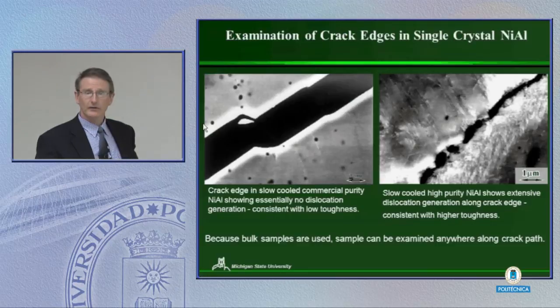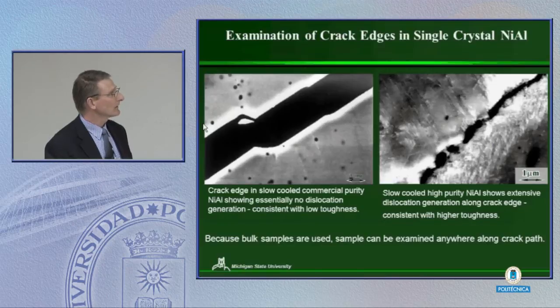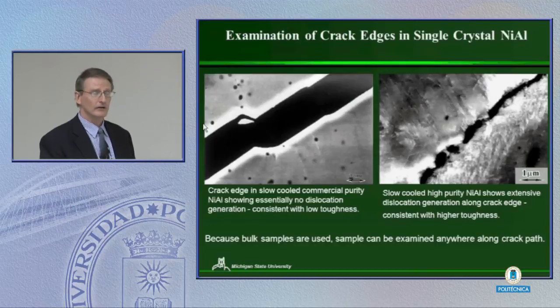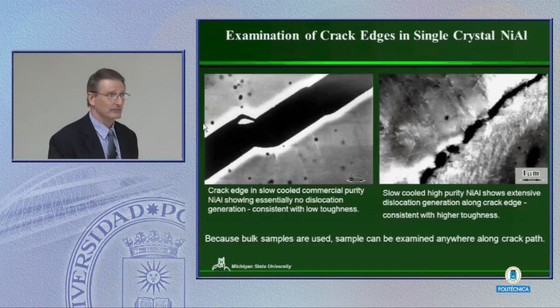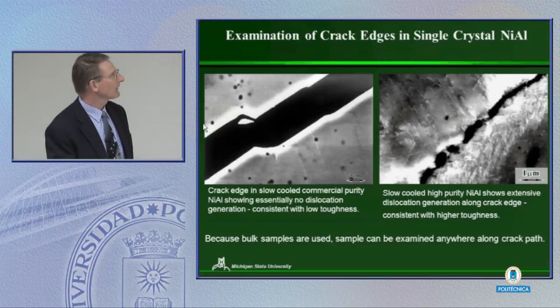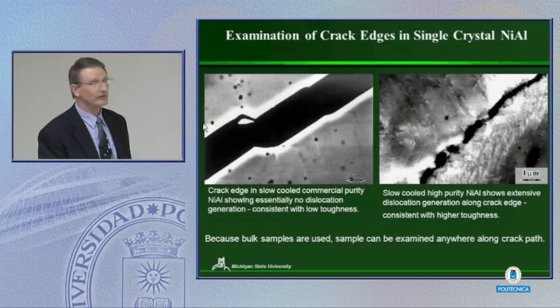The other thing, though, is because we have a bulk sample, instead of just looking at the crack tip, we can look anywhere along that previous crack. And so we get a feel for how big the crack tip was as it propagated. Here we can see in the slow-cooled commercially pure alloy, there's just a couple of dislocations along there.